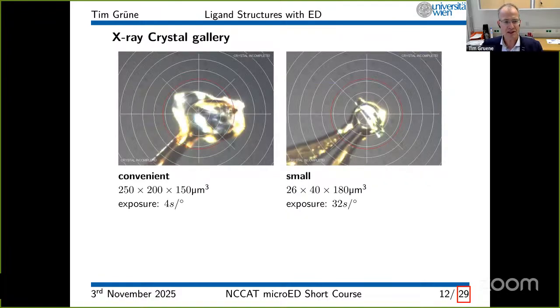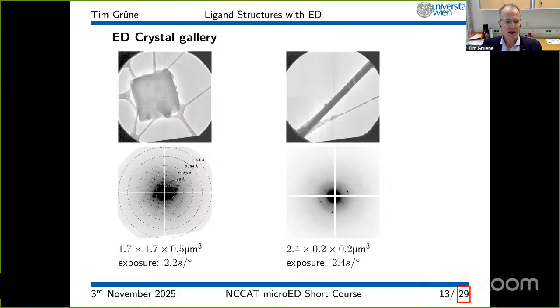A few crystals. So these are typical X-ray crystals. These are the sizes that are good. This is a 200 micrometer crystal that's good for X-ray diffraction of proteins. On the right-hand side, you see a small crystal for a protein with a synchrotron that's still quite big nowadays. Even for an in-house source, that's very convenient. The smaller your crystals get, the longer you have to expose. And if they're really, really small, less than a few micrometers, the X-ray sources are not sufficient anymore to create a diffraction pattern.